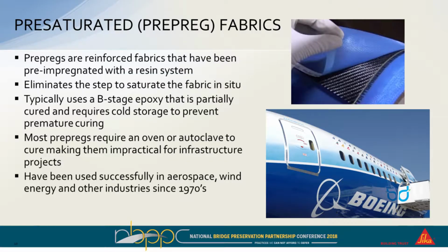So this is all done on site to create that composite laminate system between the FRP, between the epoxy and the fibers. The difference between that and what's known as a pre-preg or a pre-saturated system is that the pre-pregs are reinforced fabrics that have been pre-impregnated in the factory, in the manufacturing environment. So again, these have been used in other situations. You can see the aerospace industry has been using them for many years for constructing the fuselage and other parts of the airplanes. Military has been using these materials for many years.